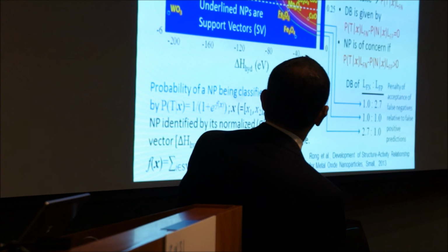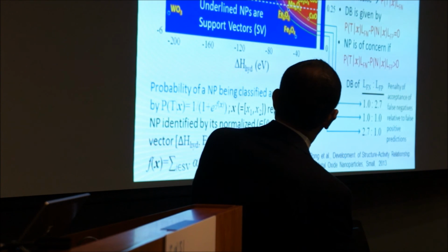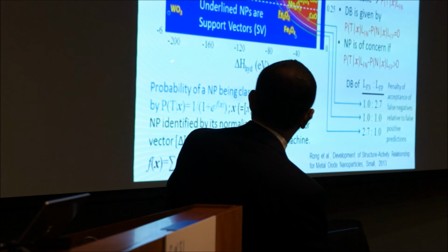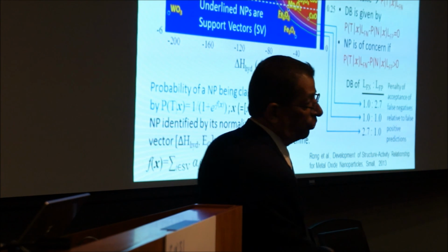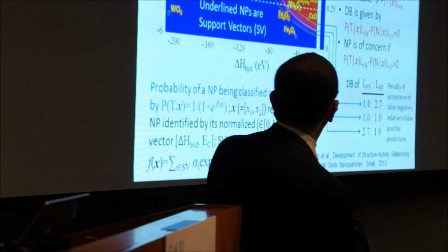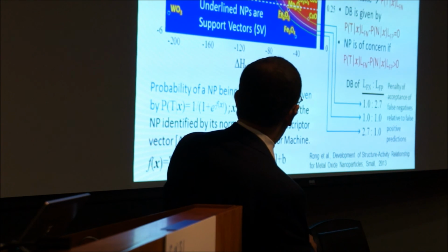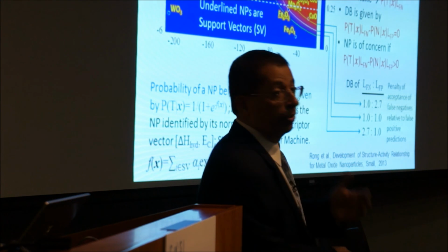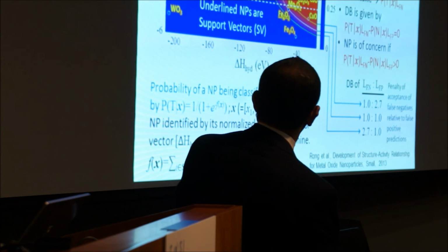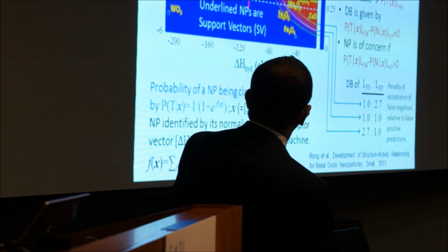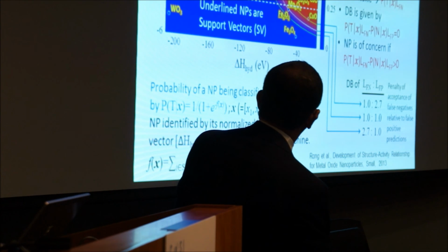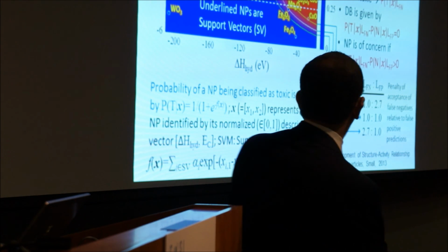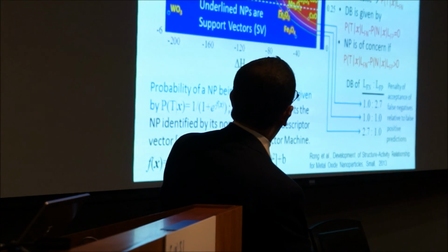Now, finally, what I'd like to say here is that the dotted line is basically the energy band gap that Andre has shown you, and what you see plotted here is the hydration energy for the metal ion and the metal oxide. So there are two factors here. Again, it corresponds to the idea that Andre talked about, which is the solubilization of the metal ion. Having a material within the band gap is neither a necessary nor a sufficient condition for the material being toxic. However, it's a very strong indicator.